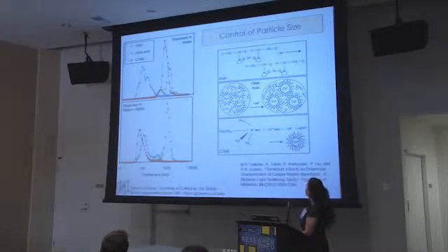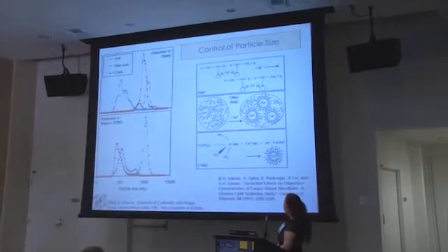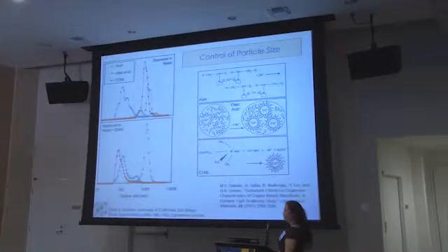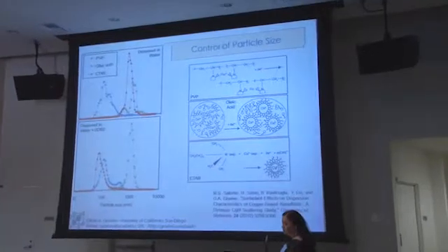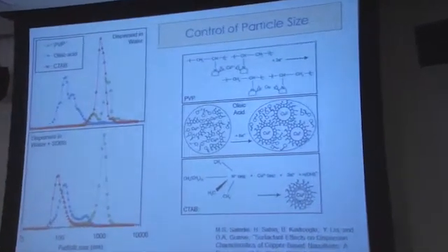For those of you that are chemically inclined, I'm showing here the chemical reactions that occur between the copper you are producing during synthesis and the surfactants you're using in the container where you're synthesizing the material. All three of these are very well-known surfactants. The top one is PVP. The second one is oleic acid, and the third one is CTAB. These are all very good materials for controlling agglomeration. CTAB happens to be particularly good.